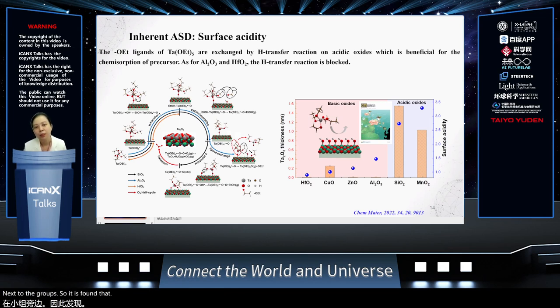It was found that the inherent selectivity definitely comes from surface acidity differences. We summarize the material differences in this figure on the right. As you can see, SiO2 and manganese oxide are called acidic oxides, while the red side is more towards basic oxides. For the basic oxides, the hydrogen transfer process is forbidden. Through that, we are able to differentiate two hydroxyl-terminated surfaces: on the acidic oxide we get normal growth, while on the basic oxide we confine the growth.